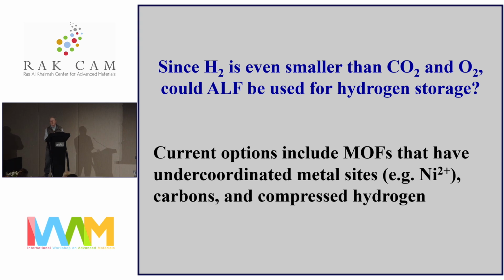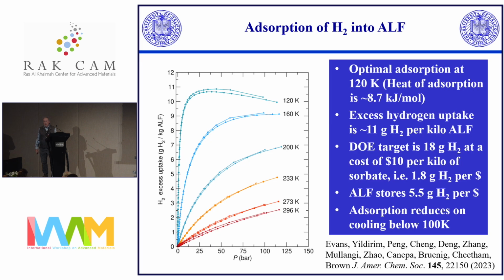And then, of course, the comparison always has to be with compressed hydrogen. And when people store hydrogen under compression, they use about 350 atmospheres normally. So that's serious pressure. So hydrogen does go into ALF extremely well. Of course, interactions between hydrogen and a framework, whether it's ALF or any other one, are typically much weaker, and so you have to cool it down more. So the optimal adsorption is at about 120 K.